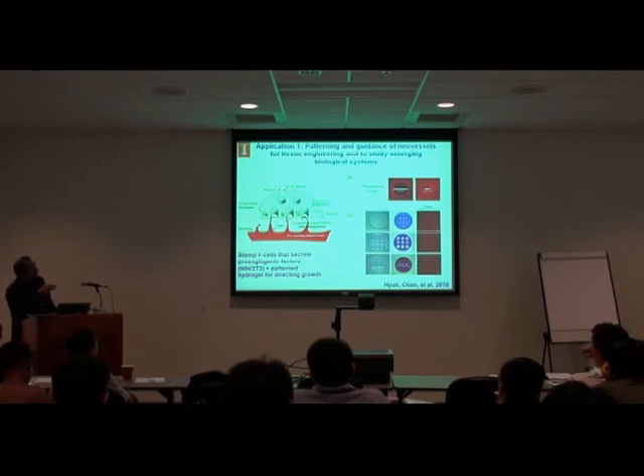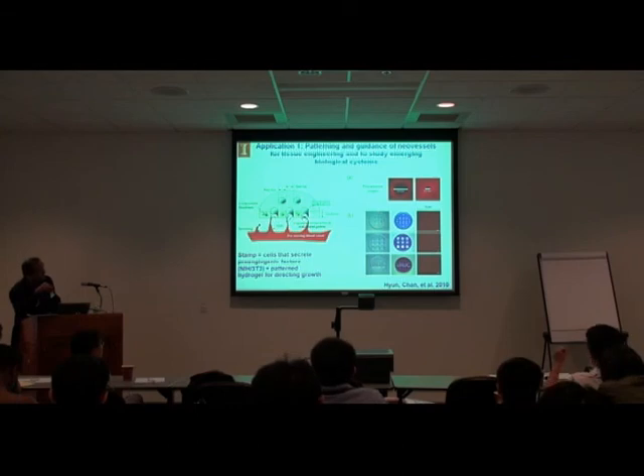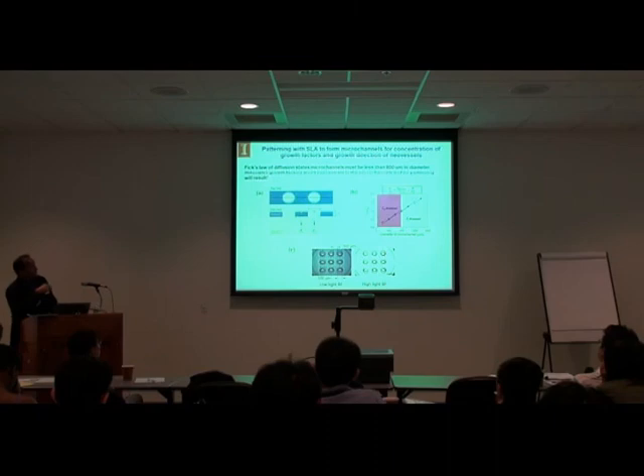So we form a structure like this, which is essentially a circular disc that's a little over a centimeter on the side. And it has these pores in it. These are large. We made them from 300 microns up to almost a millimeter, 1,000 microns. And we put these pores inside the hydrogel structure. This hydrogel has embedded cells, and the material composition is controlled. So the stamp, this microvascular stamp, we call it, has cells that secrete pro-angiogenic factors, and they have different patterns for directing the growth. So I wanted to then see what we can do with this.